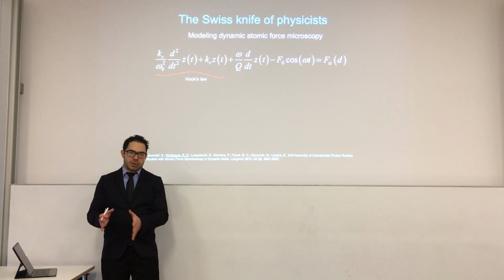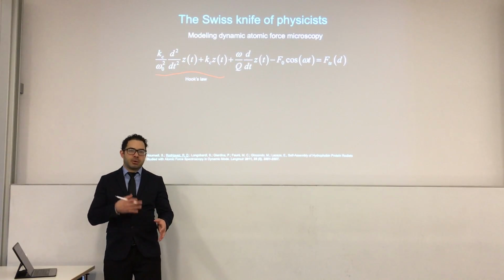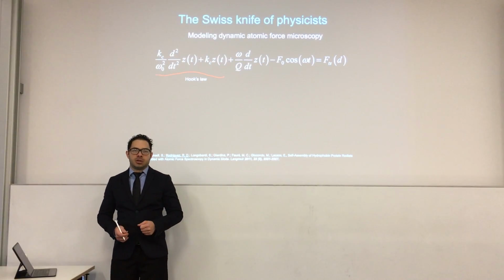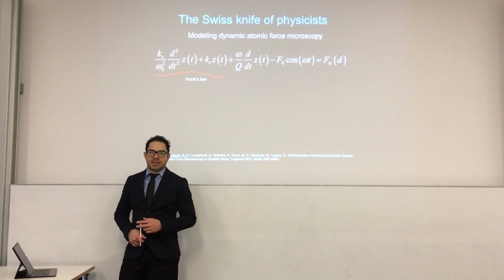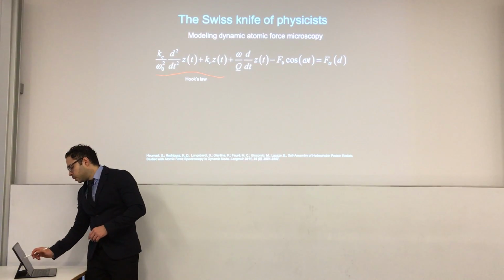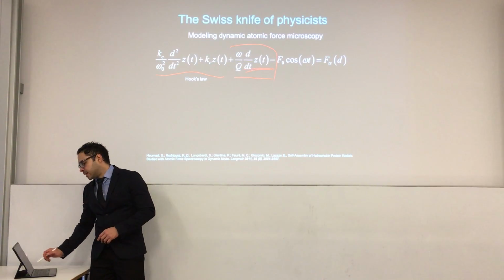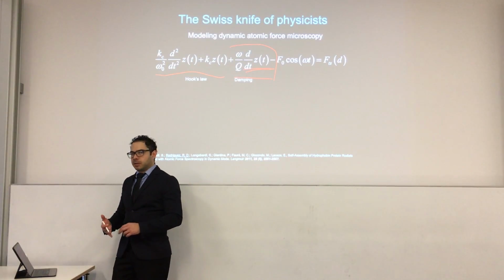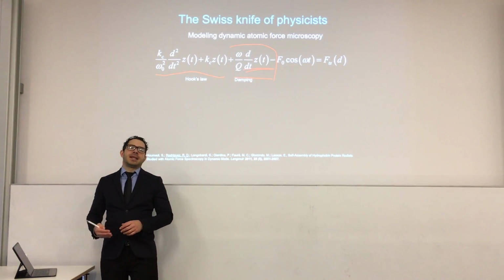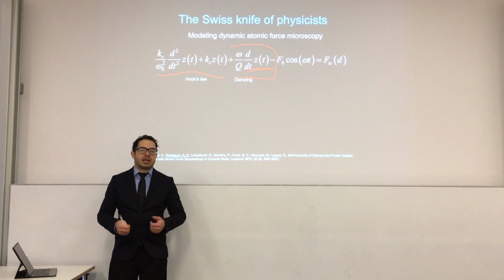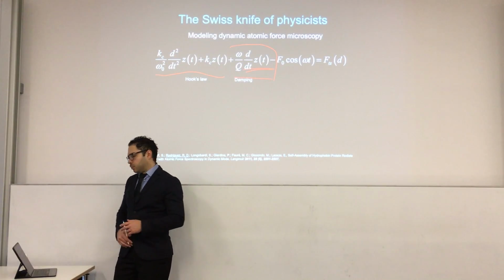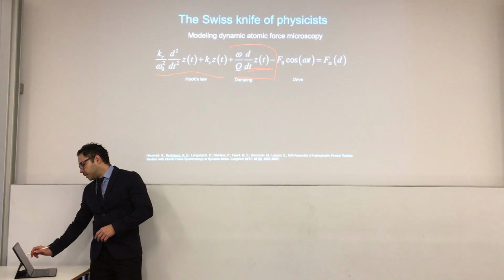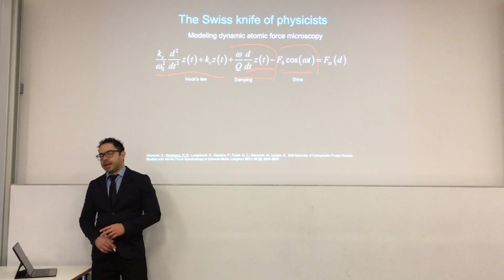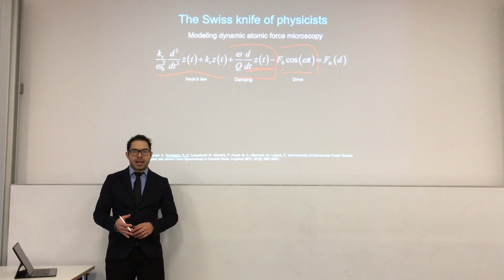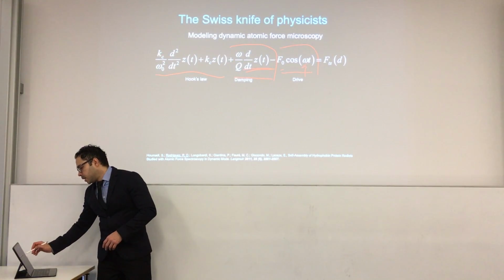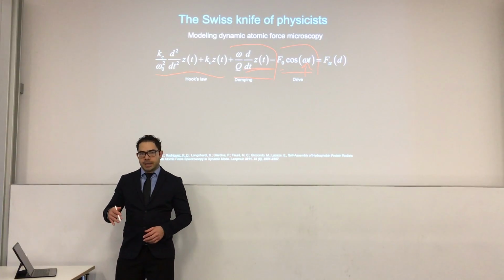It means that there is a force in the cantilever system, or the spring system. When there is a deflection, this force will be proportional to the spring constant, or the stiffness of the cantilever, times the deflection, or the deformation of the system from its equilibrium. The second part is a dissipative force. You can identify that because it's proportional to the velocity of the system, and this is due to the damping the cantilever experiences due to the interaction with molecules, for example, or in liquid if you do it in liquid. The other term that you see here is the external excitation that you apply to the cantilever at the mechanical frequency of the system in order to make it oscillate.